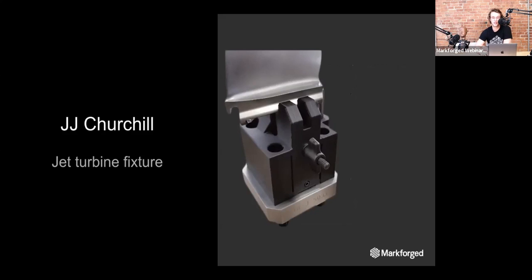So they decided to 3D print it. Typical 3D printing materials would not stand a chance at holding this turbine in place. But when they reinforced it with carbon fiber, this part, which printed on a Mark II, was stiff and strong enough to replace aluminum for 80% less money and in 70% less time.